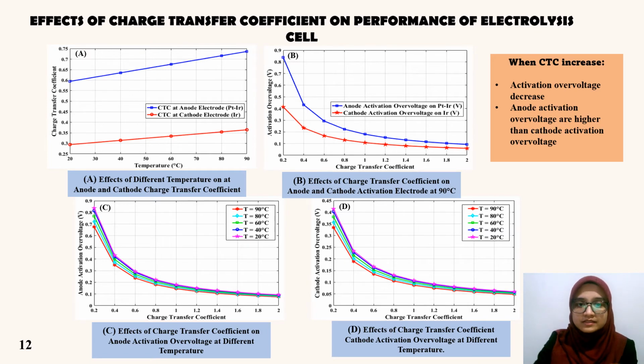Moving on to figures B, C and D, which are the simulations made on the effect of multiple values of CTC on activation overvoltage. In general, it can be summarized that activation overvoltage decreases when CTC increases, as plotted in the figures. And the values of activation overvoltage at both anode and cathode are the highest, which are 0.8374 volt and 0.4143 volt respectively, at the lowest value of CTC, which is 0.2. This is because CTC is known as the fraction of potential energy that is applied to the electrochemical reaction, and it will cause the reaction rate in the electrolyzer to increase. Therefore, when the value of CTC increases, a smaller amount of activation overvoltage is required for the reaction electrokinetics to occur at the electrode.